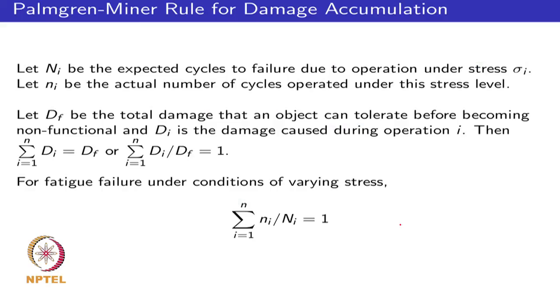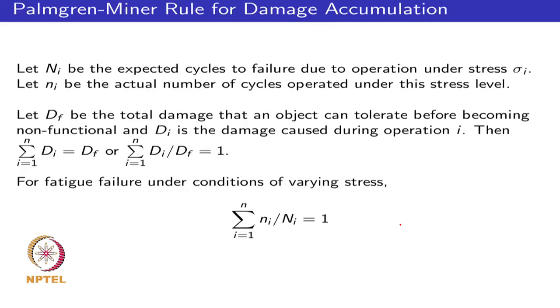For example, you might have a situation where you apply stress 1, which is larger, and stress 2, which is smaller, and your total damage at the end point after application of stress 2 might be something. And you could reverse the sequence. You could apply stress 2 first and then stress 1. So the accumulation of damage assumes that you get the same level of damage irrespective of whether you apply the larger stress first or the larger stress second. So you are neglecting sequence effects, because if you have already damaged the component, applying the same stress might cause further damage. So this is an approximation, but it gives you a way of looking at how to accumulate damage when you are operating under conditions of varying stress.